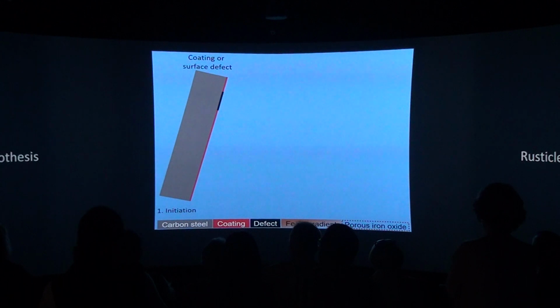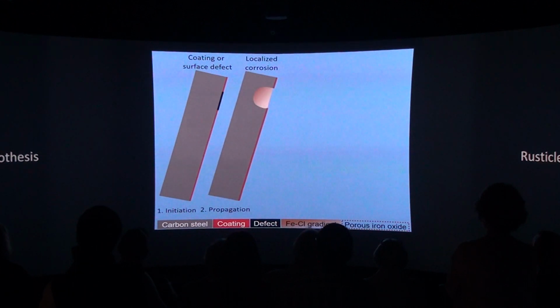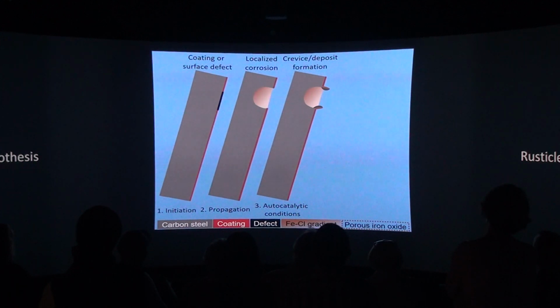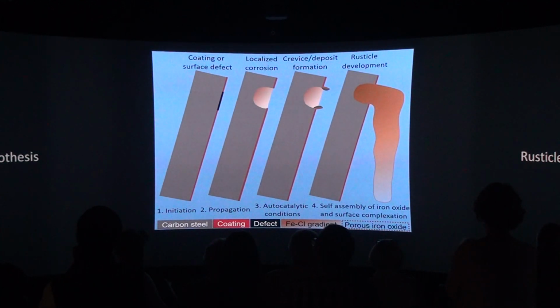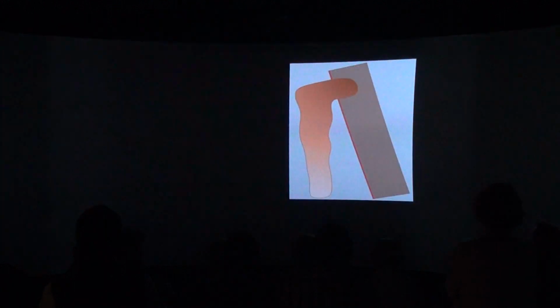So this is my rusticle formation hypothesis. It needs a coating or surface defect where the localized corrosion process starts. It forms a crevice. All this localized corrosion starts leaching iron chloride, and it deposits at the mouth of this crevice or this little cavity, and then it develops this rusticle with a gradient of iron chloride inside, keeping the rusticle, let's say, alive and growing.